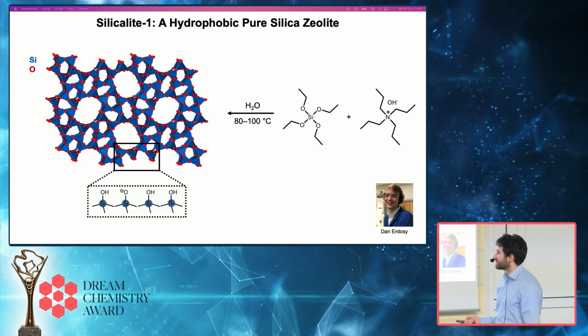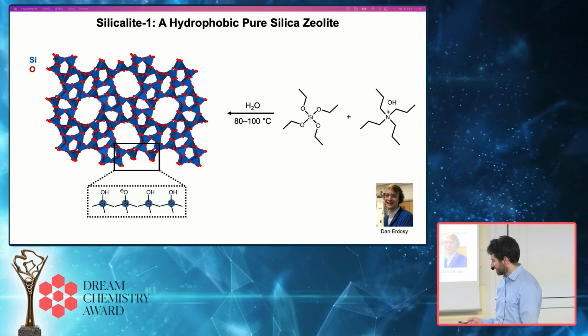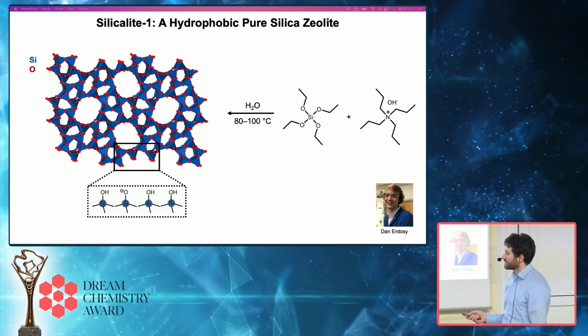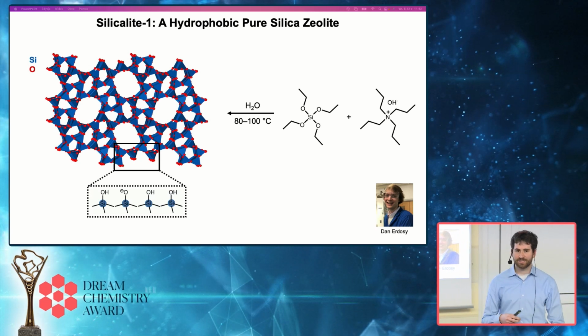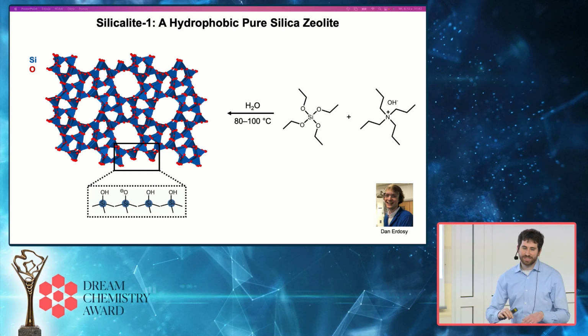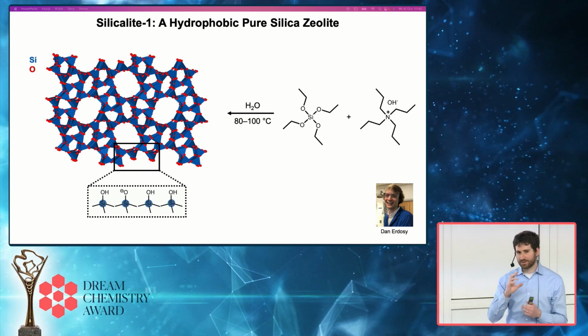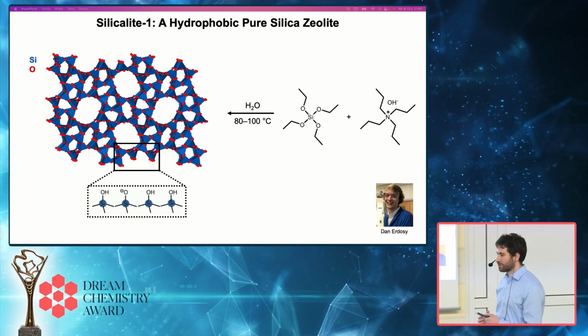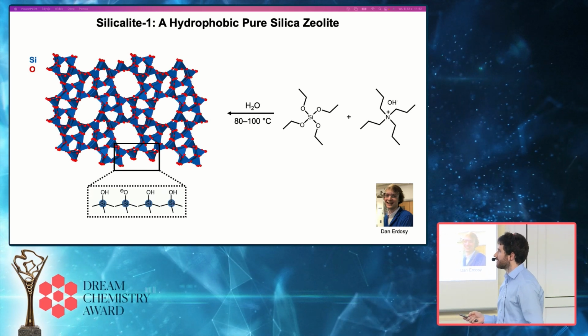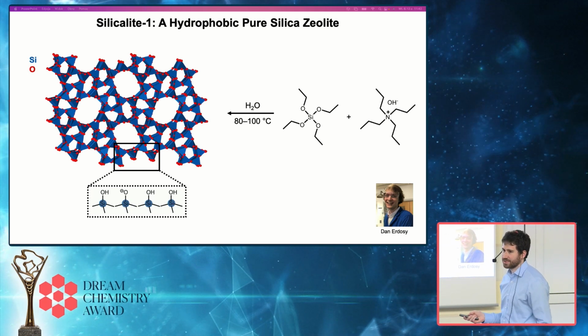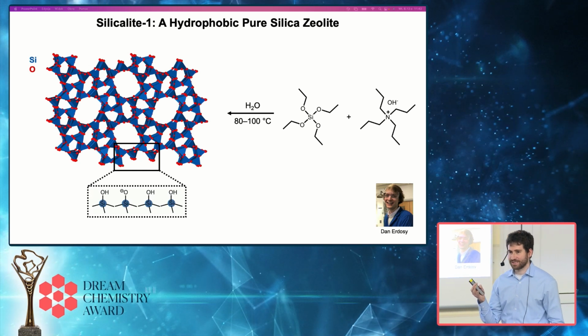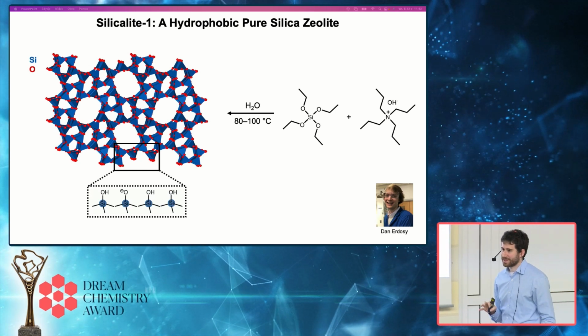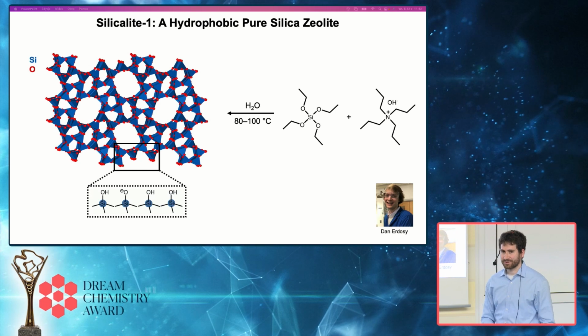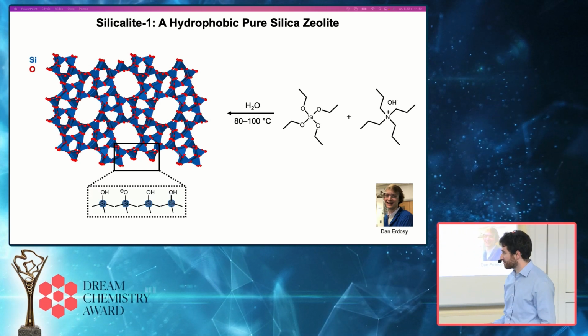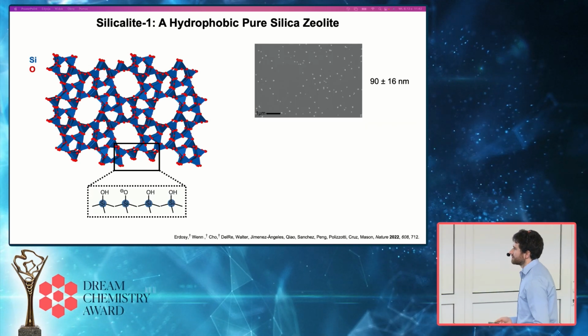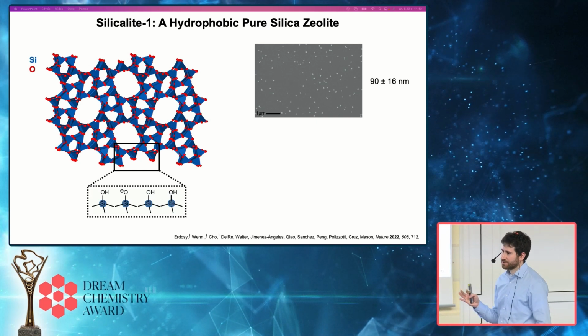These zeolites are made by combining a silica precursor, in this case tetraethyl orthosilicate, with some type of organic structure directing agent, in this case tetrapropyl ammonium hydroxide, which basically the silica crystallizes around the organic cation, which templates the pores. The challenge with doing this is that you then need to remove the organic structure directing agent, which is usually done by heating at really high temperatures, but you need to be able to do that without irreversibly aggregating the nanoparticles in the solid state, and that requires a fair bit of optimization, which Dan was able to do to be able to make nanoparticles of a variety of different sizes.